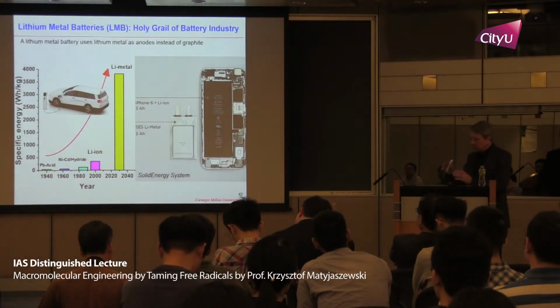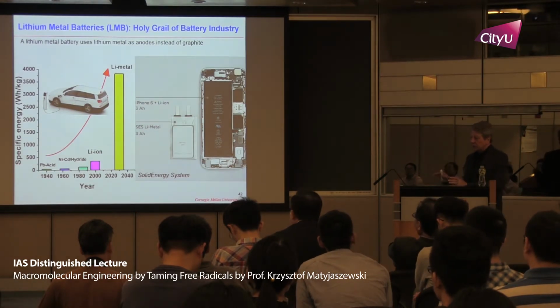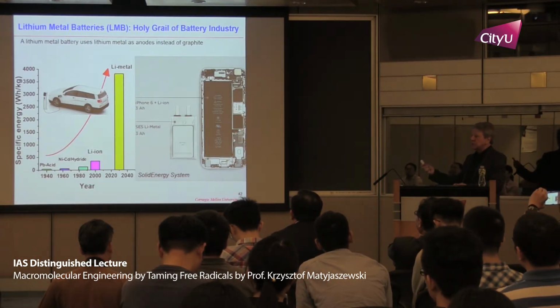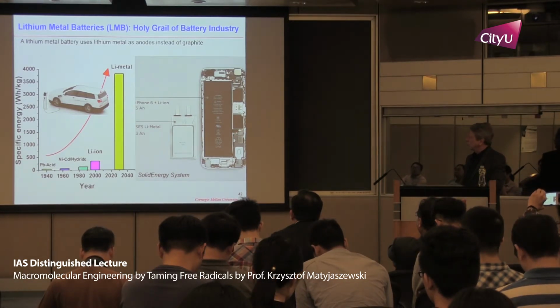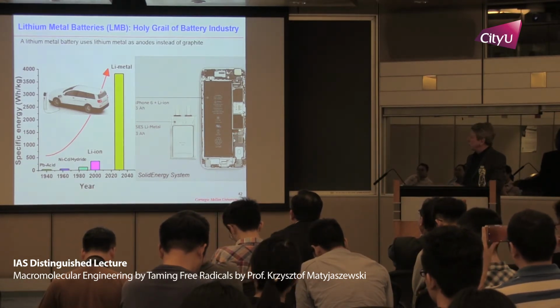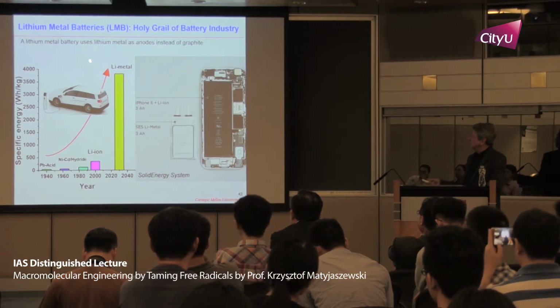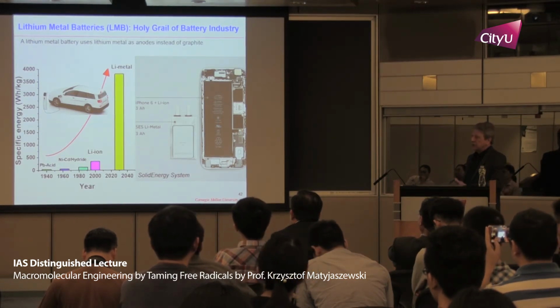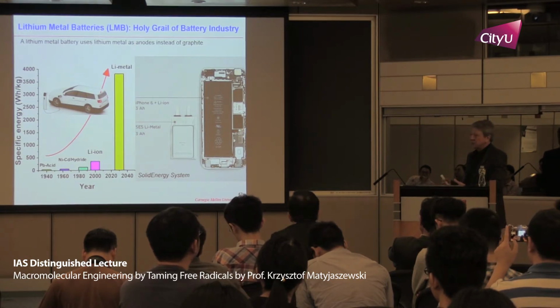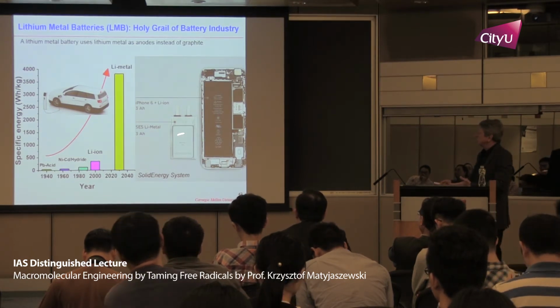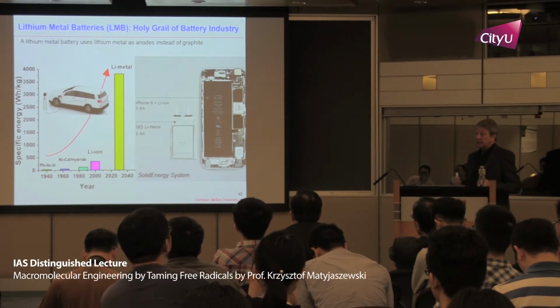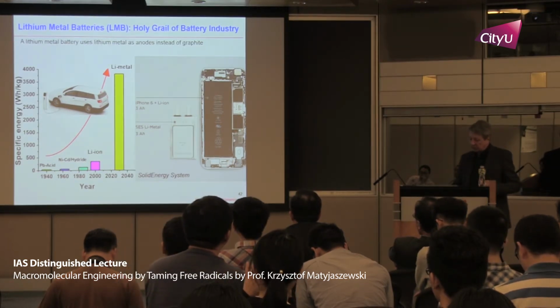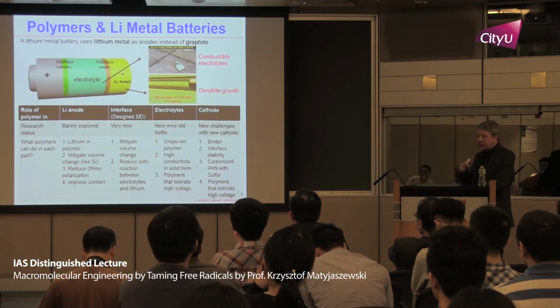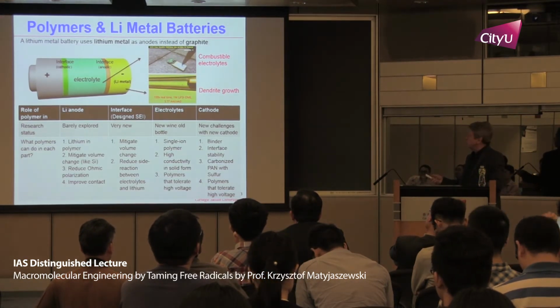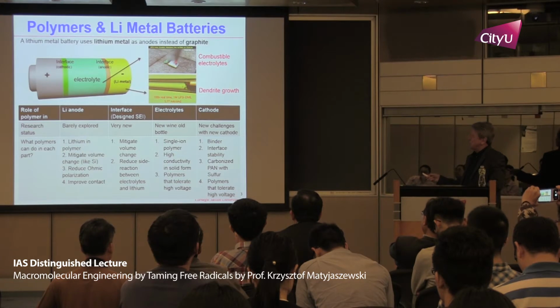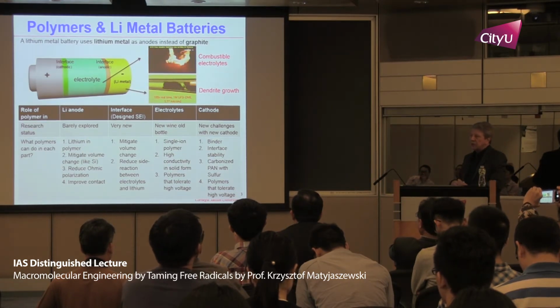So I wanted to finish with some examples related to lithium batteries, because some of these carbon-based systems can act as the electrodes, but of course the challenge is how we can go from lithium-ion batteries to lithium metal batteries. In that case, you will have a much larger specific energy density and smaller size and lower weight and potentially much better systems. So typically, if you start with lithium metal batteries and if you have a combustible electrolyte, any kind of damage gives fire.